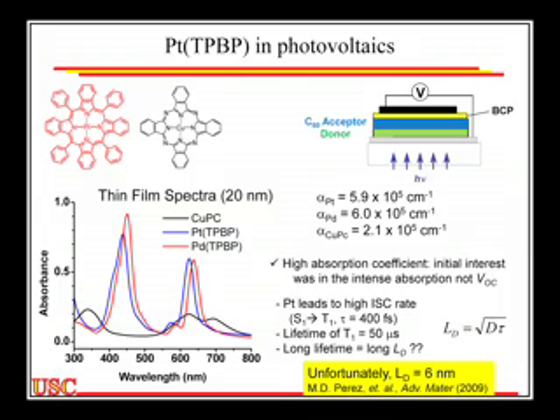I'll talk about this later, but we know the intersystem crossing rate is quite fast. So the question is, does it give a long diffusion length? No, it doesn't at all. It's quite short, actually. It's about 6 nanometers. This has to do with trapping, and it's a whole other part of a seminar I don't want to get into, but the interesting thing is where this led us in terms of the chemistries that we did to develop better chromophores for longer wave absorbers for platinum and other compounds.